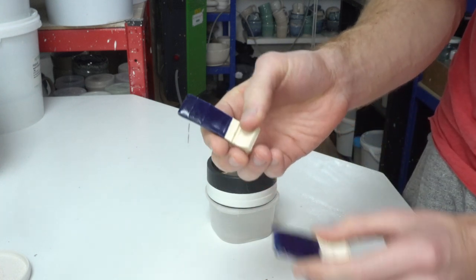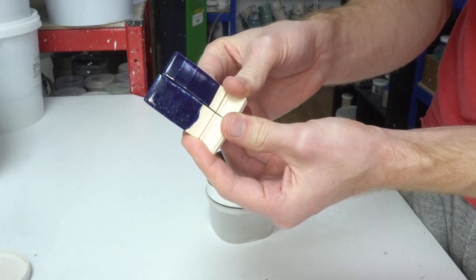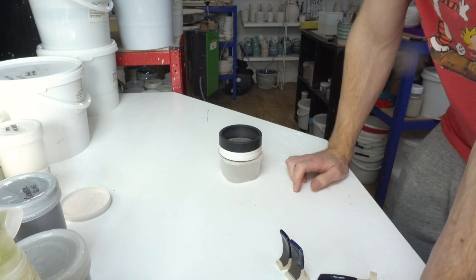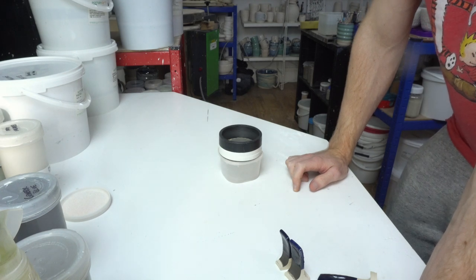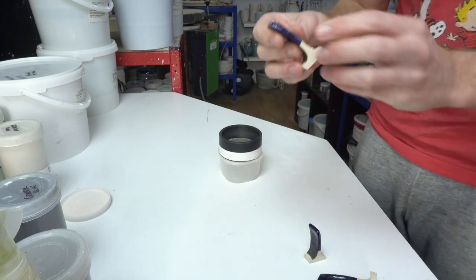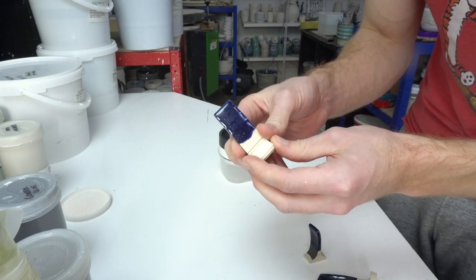And then that's the blue. And that's the blue with, I didn't quite have enough for 3% sprinkles in that. So I think that's too blue, it's got lots of cobalt in it. So what I've done is reworked the glaze slightly. There's a bit more manganese, a tiny pinch of chrome and half the cobalt. So it should be more blue gray than this pure cobalt blue.